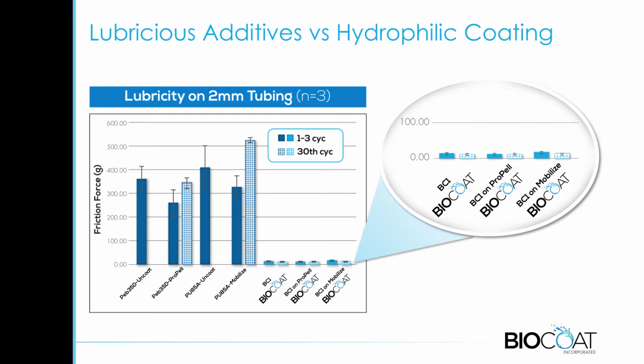However, as you do cycling it back and forth 30 cycles, these have kind of bloomed to the surface. You can see that they've kind of worn off. And so by the end of it, they're about the same as an uncoated device. Then if you look at ones that we've applied a hydrophilic coating on, you can see that there's a substantial reduction. So it's not just a 25%, it is a 95% plus reduction in that friction, and very durable throughout those 30 cycles.